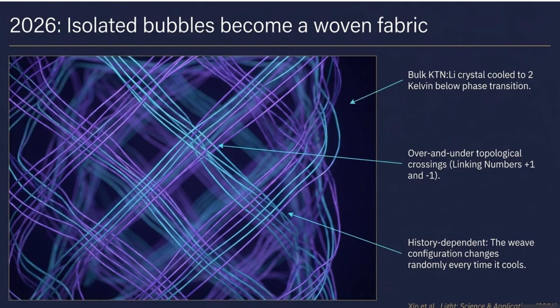But what's even more fascinating is what happens if you want the weave back. Oh, you can get it back. Yeah, but you can't just shine a different light to reweave the exact same pattern. What you can do is thermal cycle the crystal. If you heat the crystal back up above its Curie point, the domains dissolve. The compass needles randomize. Okay, so it melts the structure, and then if you slowly cool it down again, passing through that crucial 2-degree window, the spontaneous symmetry breaking happens again. The fabric weaves itself anew. Yes, but, and this is key, it weaves a completely different randomized realization. Oh, wow. The pattern of over and under crossings, the distribution of those linking numbers, it is entirely new. That is incredible. The structure is history dependent.